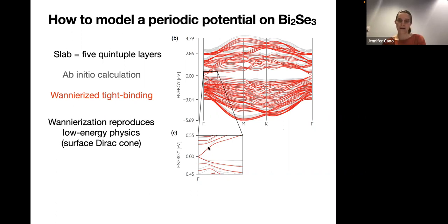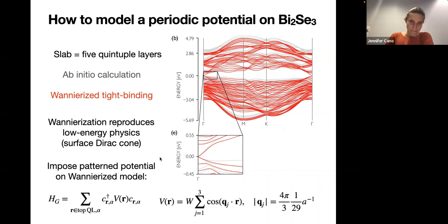We use this tight binding model to figure out which orbitals have weight on the surface. If we apply a potential on the surface, which orbitals are going to feel that potential? That's exactly what we do. We take this tight binding model and we add a spatially modulated potential. For the results I'm going to show, we consider the length scale to be around, I think, 11 or 12 nanometers. We picked that because that was the length scale of twisted bilayer graphene, so we thought that might be a good length scale to consider, even though it's a bit smaller than the currently accessible dielectric patterning, like I was showing from Corey's group.